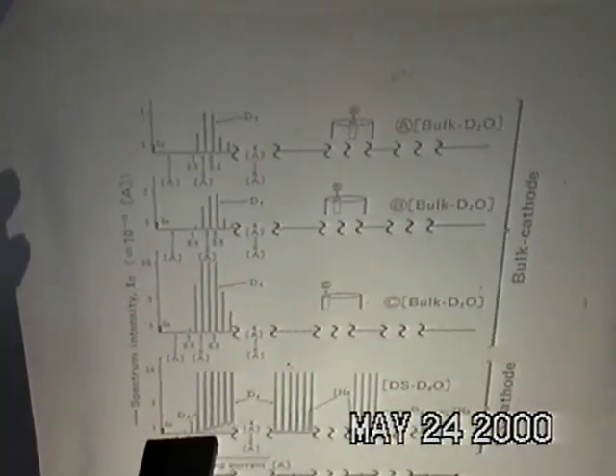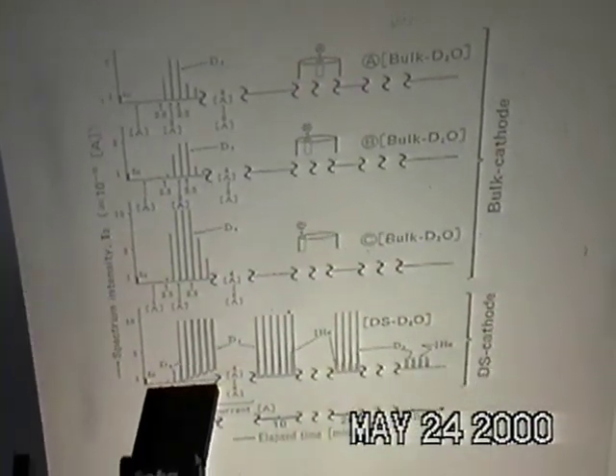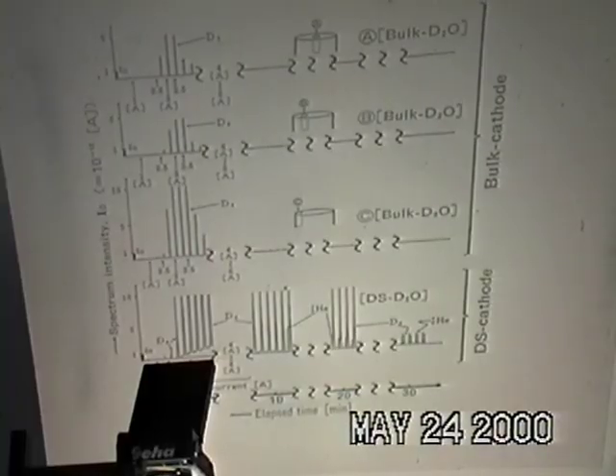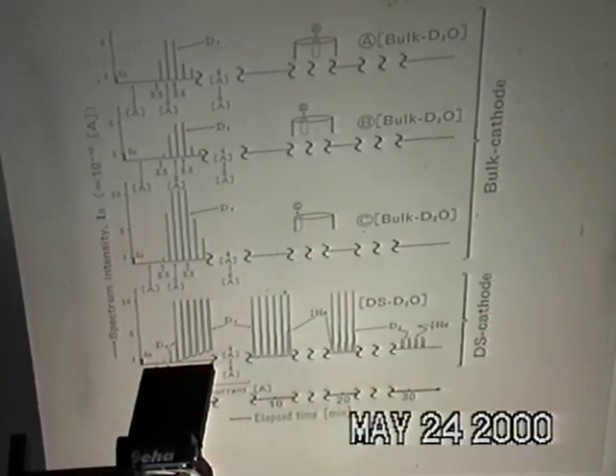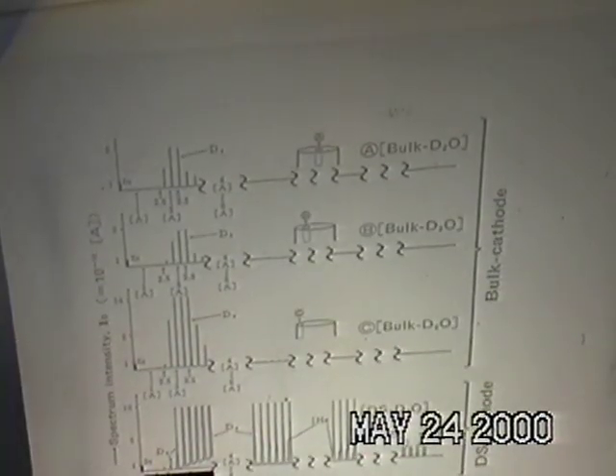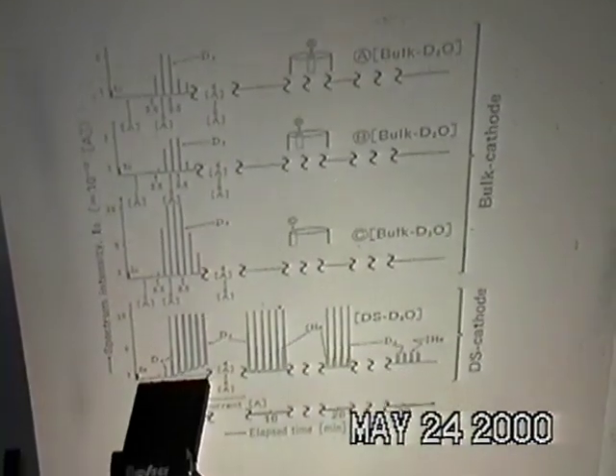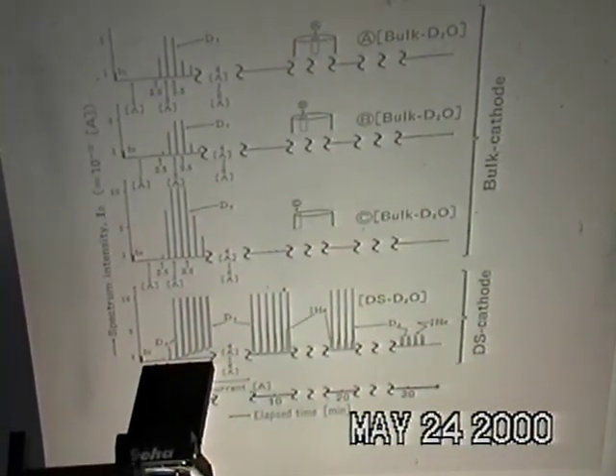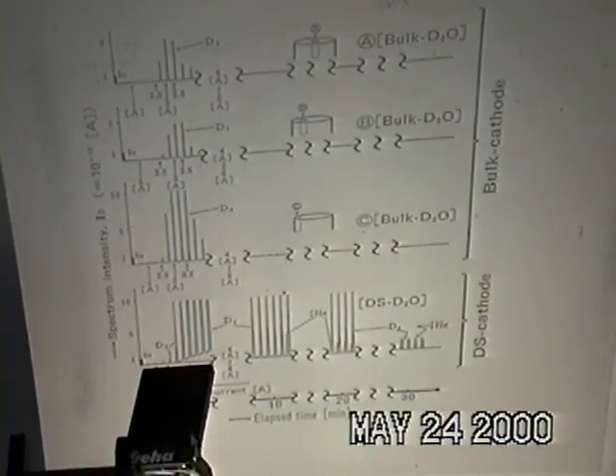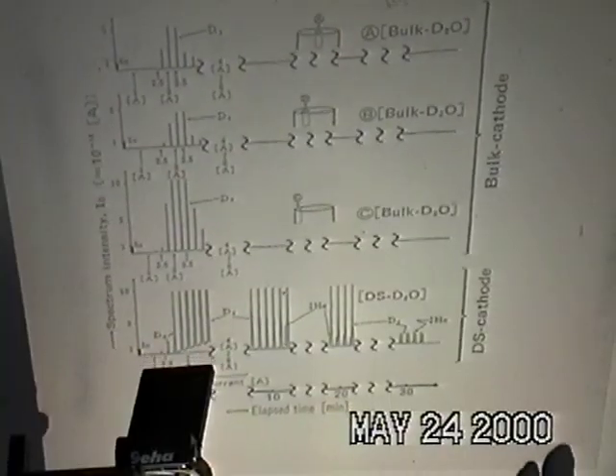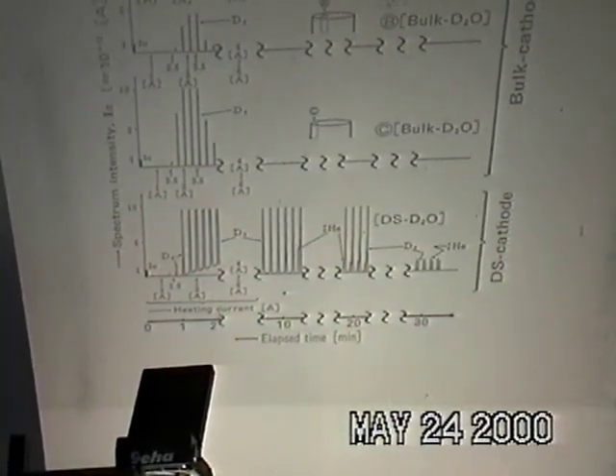In order to investigate further the difference between the bulk cathode and DS cathode, we measured the deuterium concentration of both cathodes by using a quadrupole mass spectrometer. First, we made the sample powder of bulk D2O, as shown here. We drilled 3 zones of the cathode: the A zone is the center, B is the middle, and C is the edge. As shown in this diagram, 3 kinds of powder samples of bulk D2O and a palladium black sample of the DS-D2O were heated under the same condition.